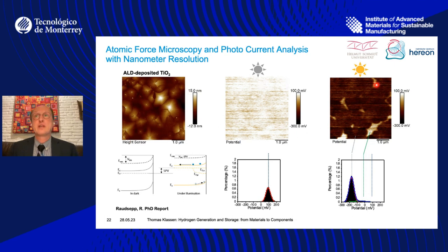And taking a closer look, we can tell that the amorphous regions, these are amorphous regions in our coatings, don't do a good job in photocatalysis and photoelectrochemistry. But the crystalline areas are much more effective, and there are even certain crystalline orientations that give us more photocurrents.